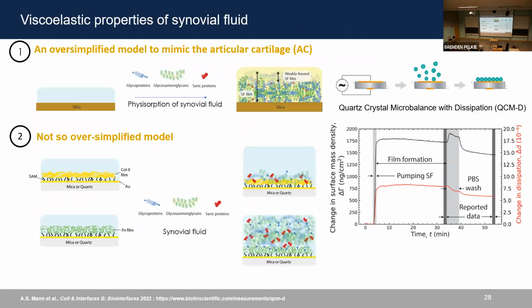And so some of the work that our lab has done is mimicking the surface interactions in different types of models. In a very simplified model with just silica or mica or a quartz crystal, synovial fluid components are physisorbed, and using a quartz crystal microbalance with dissipation, we can monitor in real time the formation of the thin layer, as well as the retention of it. And from the dissipation, or the loss of energy information, we can also model the shear compliance of the thin film.